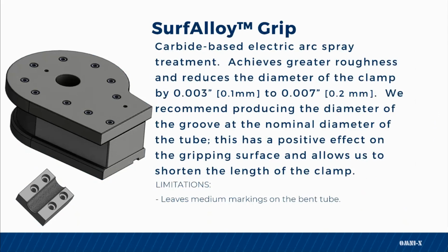Surf alloy is a carbide-based electric arc spray treatment. Surf alloy achieves greater roughness and reduces the dimension of the clamp by 0.003 of an inch to 0.007 of an inch. We recommend producing the diameter of the tube groove at the nominal dimension of the tube. This has a positive effect on the gripping surface and allows us to shorten the length of the clamp. Surf alloy grips leave medium markings on the bent tube.